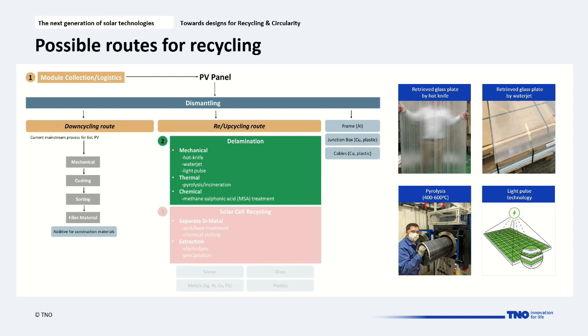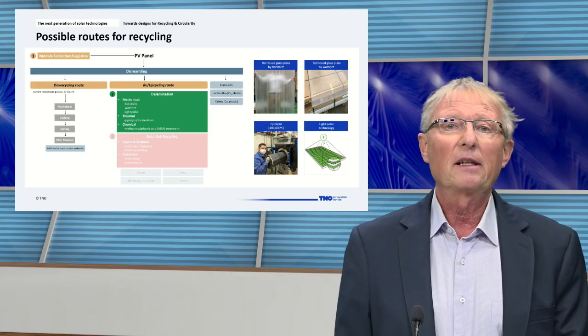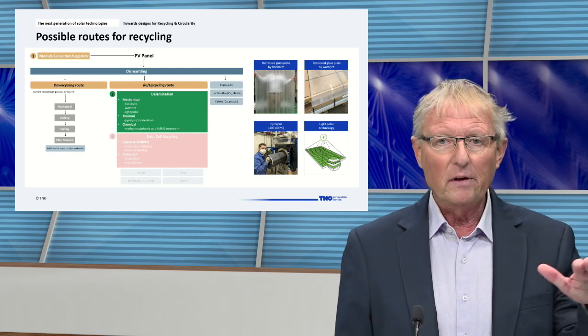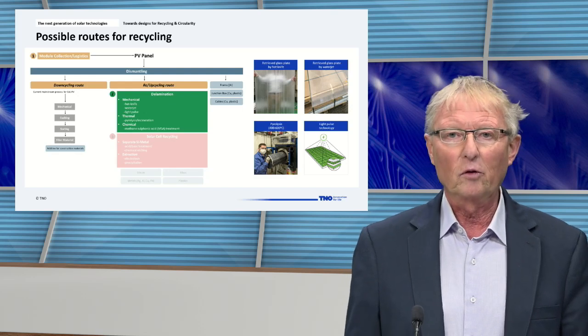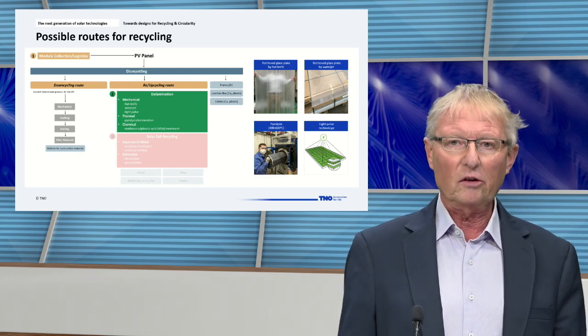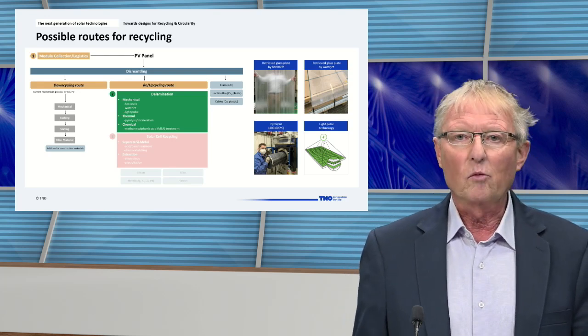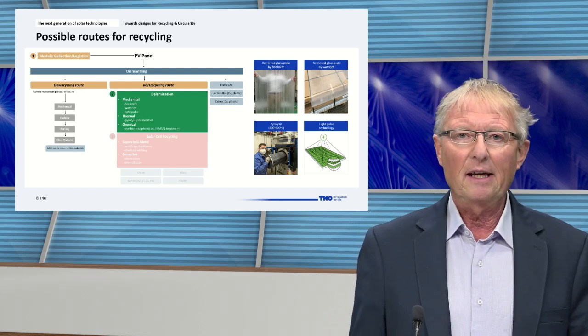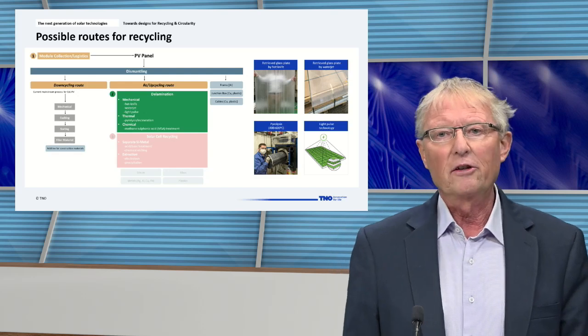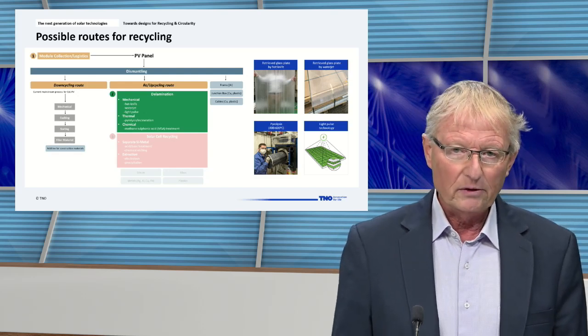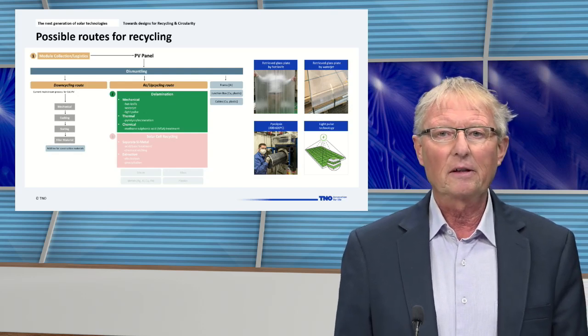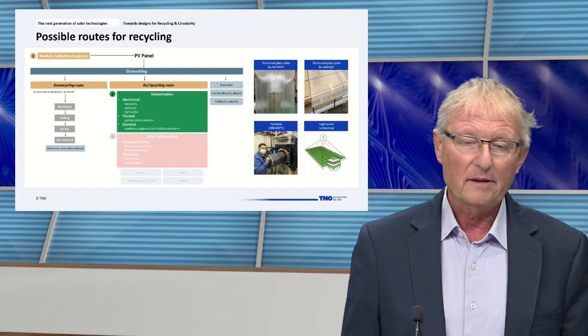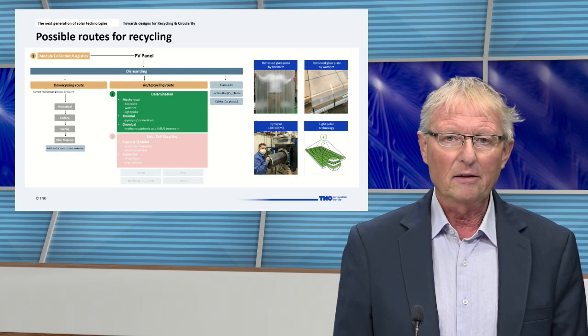There is just a better way. That is the delamination. That's one up. And that consists of a mechanical, thermal, and chemical treatment. In the upper left photo, you can see the technology of the hot knife. The hot knife is a knife that is heated at 300 degrees and cleaves through the panel to take off the glass plate. But as you can see in the photo, it's still contaminated with encapsulant. So it's not residue-free. There's another technology, which is a water jet, that could help here and be a bit cleaner. And there is also a low energy, high intensity light pulse technology of 1 millisecond at different wavelengths, which act on the surface of the substrate to delaminate the components layer by layer.